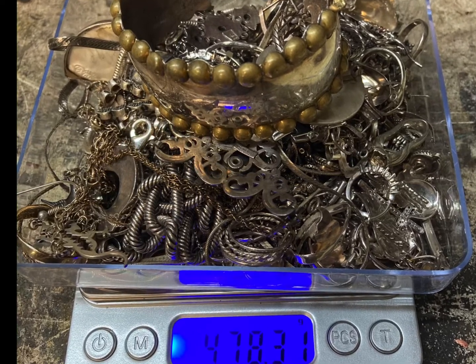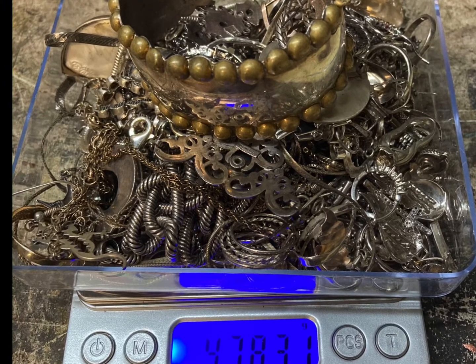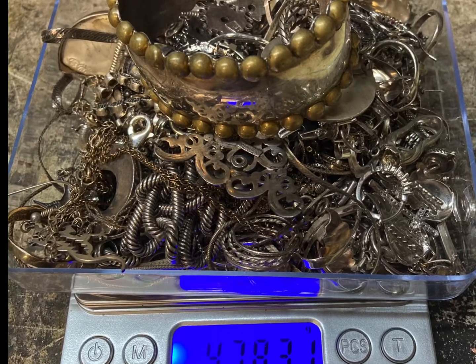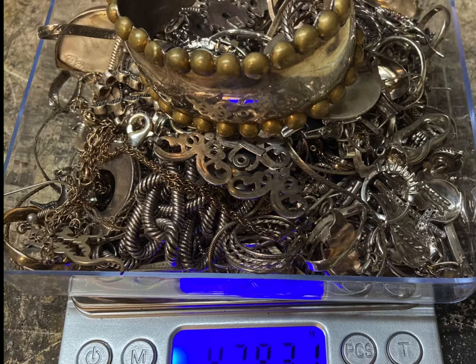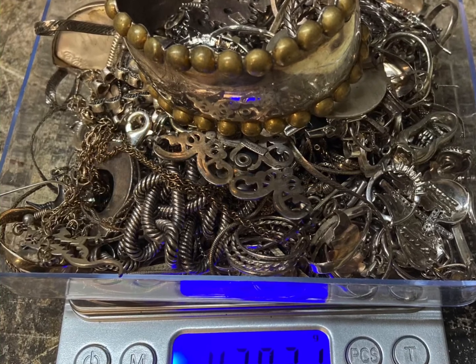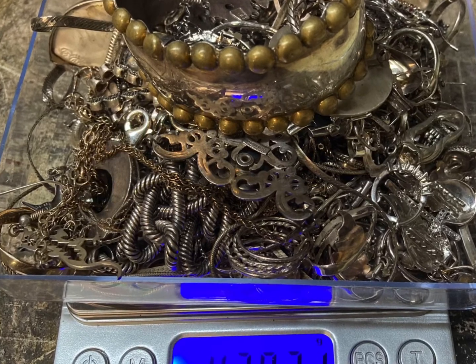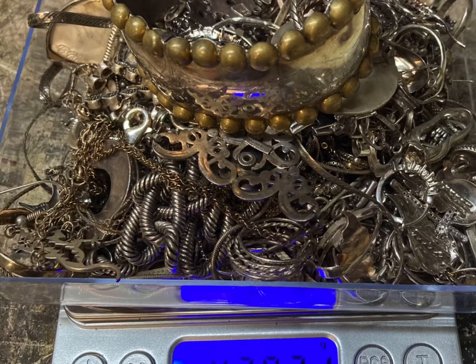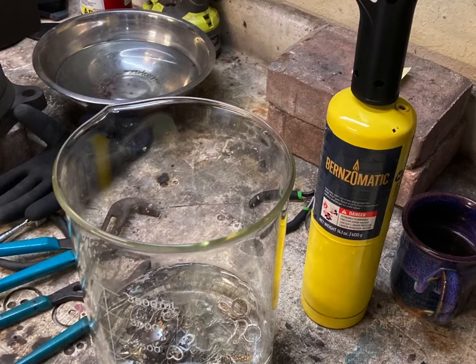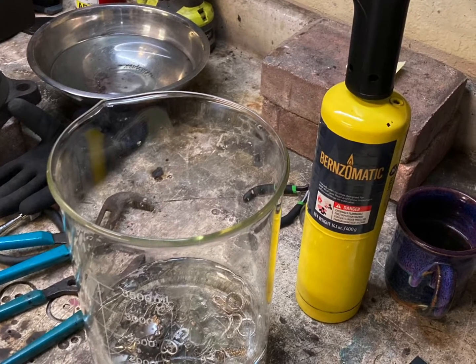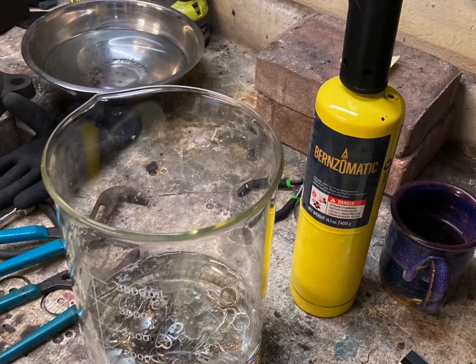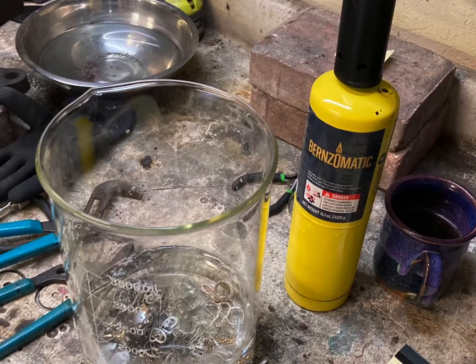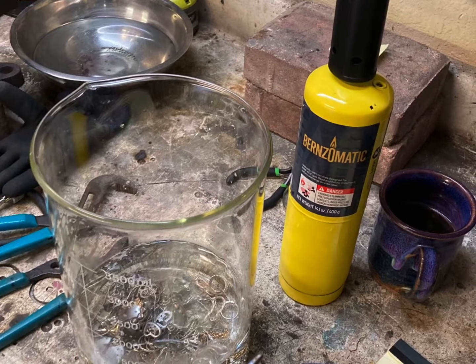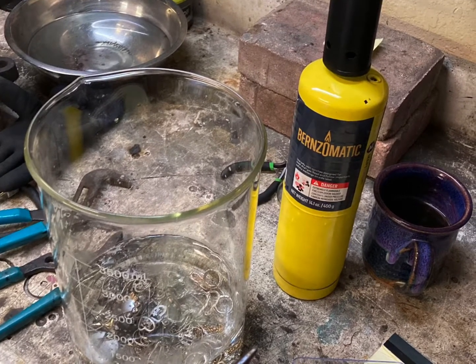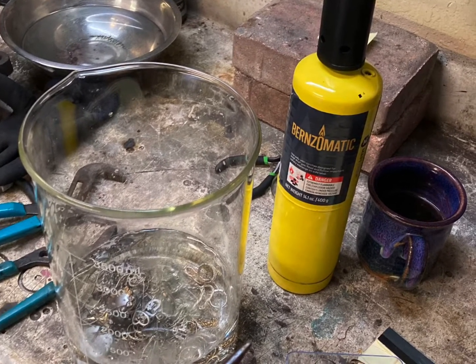And the first step in anything is to remove the springs and to remove the stones and then to burn off any waxes or oils that are left on the 925. If you don't do this, you will end up with this weird brown mixture in your solution. It's a pain in the butt. You end up having to double refine it. So the best thing to do is just take a few minutes and really pull out everything you can.